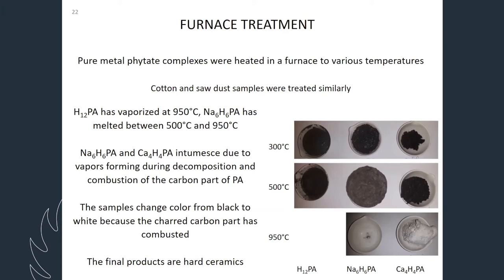What we did, we made the pure phytic acid and their metal salts and put them in the furnace, say 200 degree, 300 degree till 1000 degree at 100 degree interval. We prepared the cotton samples and sawdust sample treated with flame retardant, and we also treated them in the similar way. Here we are showing the pure samples at 300 degree, 500 degree, and 950 degrees.